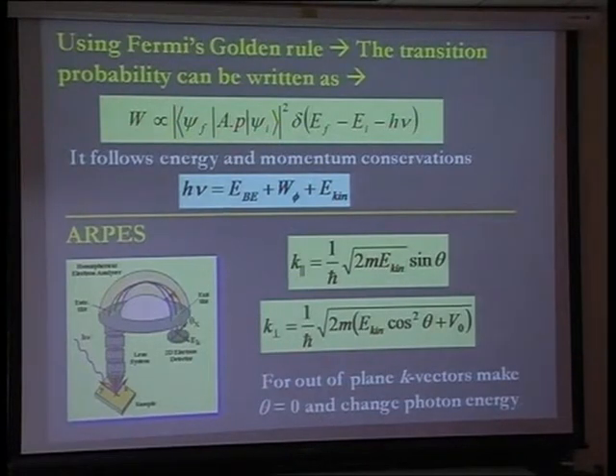So once you know the angle, you can see that velocity or momentum is a vector, so you can find out the out-of-plane component and in-plane component, and you know the kinetic energy. So using these two pieces of information, you can map the K parallel and K perpendicular. K is the reciprocal lattice vector, using these relations. So here, if theta equals 0, your K parallel becomes 0, and K perpendicular becomes like this, plus V0, which is the inner potential.